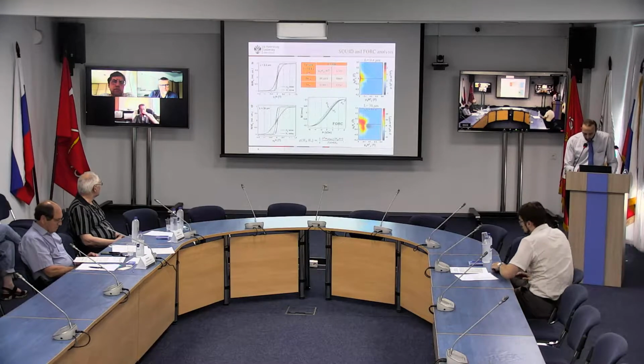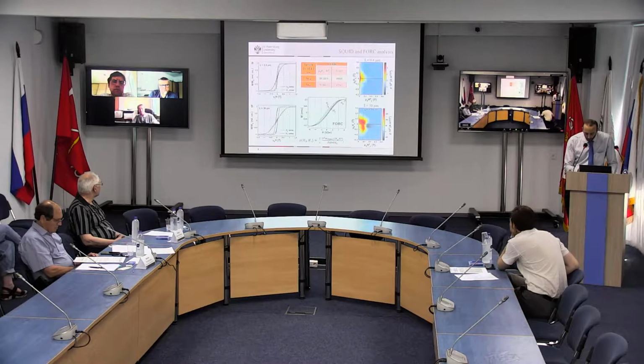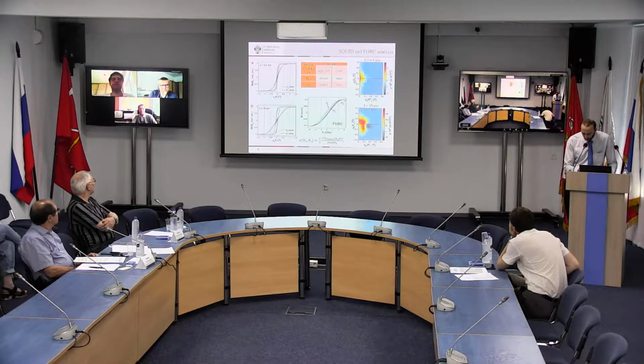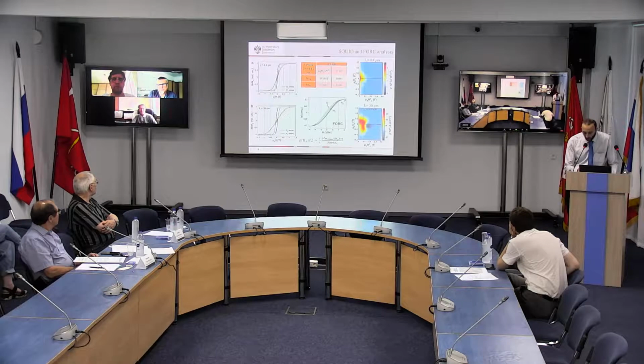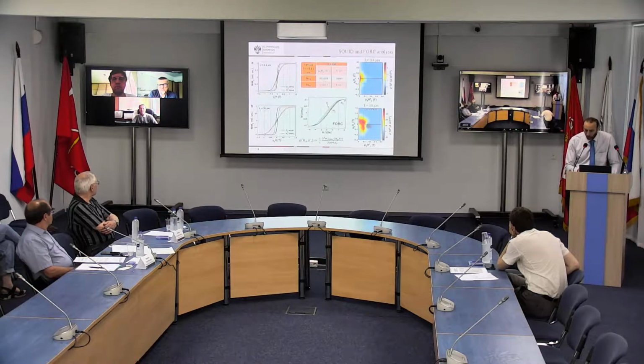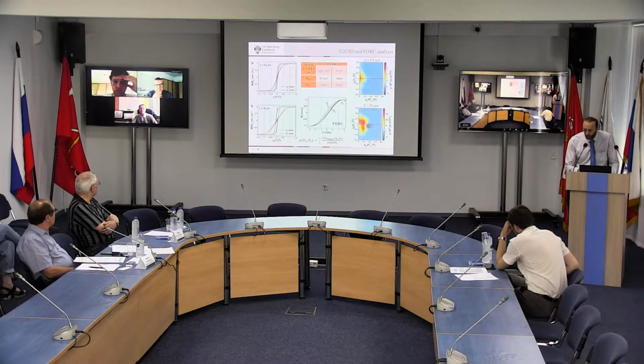This method, or FORC method, implies calculating a change in the first-order reversal curve slope that can be associated with so-called interactions and switching fields in the system. You can see in the upper graph the result of FORC for a short nanowire, where the peak close to 0 is related to nanowires remagnetized due to the presence of a harder nanowire in the array. Also, this non-uniform, not fully symmetrical pattern may point to the existence of inhomogeneity. Also, that may be the reason for the expansion along the switching field axis.